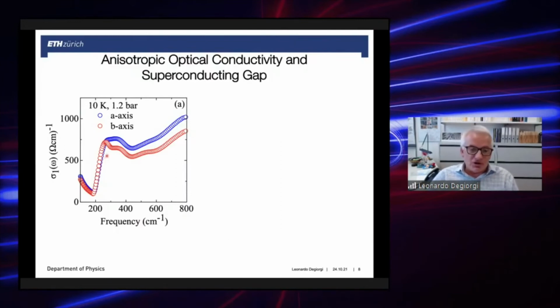Such a behavior can be very nicely accounted for or reproduced by the Mattis-Bardeen approach, which is the conventional description of the real part of the optical conductivity for an s-wave-like superconductor within the BCS framework. And in fact, this is a very straightforward procedure, which is pretty well established in the literature. You can fit the measured spectra very nicely with this Mattis-Bardeen approach. You can even reproduce in quite great detail the observed anisotropy.